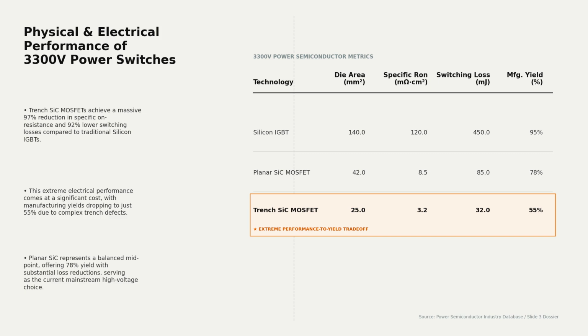Furthermore, trench devices reduce switching losses by 92.8% compared to silicon-insulated gate bipolar transistors. However, these physical advantages are offset by a low 55% manufacturing yield at the 3,300-volt rating. This low yield inflates unit costs and limits widespread market adoption. Until crystallographic defect rates are resolved, legacy silicon and planar technologies will remain dominant in cost-sensitive grid applications.